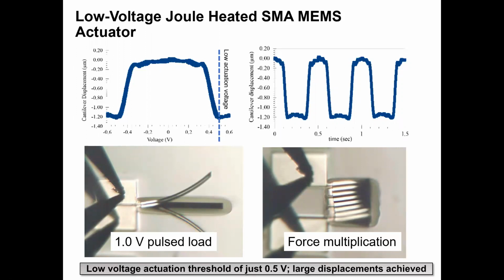The figure in the upper right shows a pulsed actuation, which confirmed the reversible nature of these deflections. And the videos at the bottom show some demonstrations of the utility of these microactuator configurations. The lower left figure shows the behavior of the two-way shape memory effect using a pulse voltage of 1 volt, which is still a significantly low voltage. The deflections are rather large at this MEMS scale and require small voltage thresholds to initiate the actuation. When these cantilevers are arrayed in parallel, such as in the figure to the lower right, the force would be expected to increase. In this case, actuation is still fast and large, but the nature of this project was not so much concerned with applied forces, so these measurements were not pursued in this dissertation.